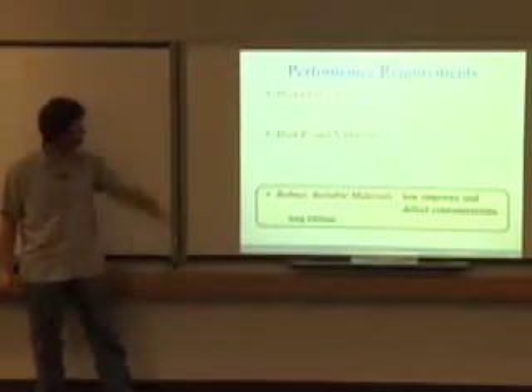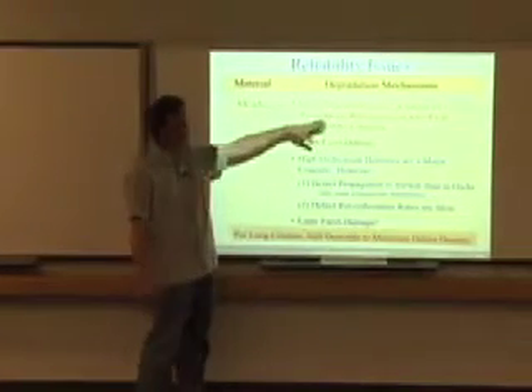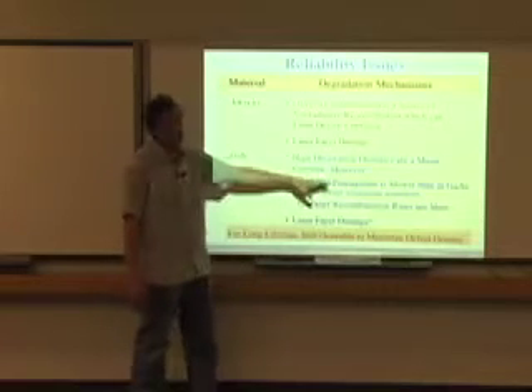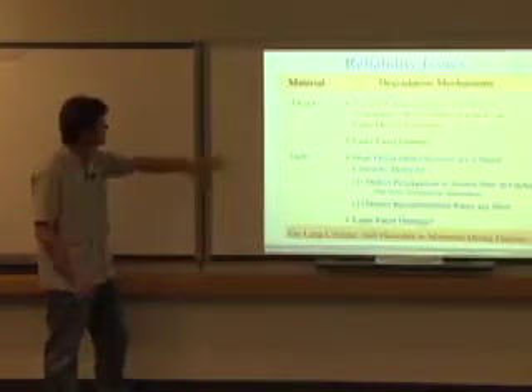So finally, performance requirements, of course, for CW operation and commercial realization, you want robust, reliable materials. In AlGaAs, you have oxygen contamination because of the aluminum, non-radiative recombination, which can occur, laser facet damage, or typical issues. For gallium nitride, of course, we worry about the high dislocation densities. However, defect propagation is slower in gallium nitride. It's a tougher material. Defect recombination rates are slow as well. So even though the defects were very high, it was mitigated by some of these. So actually things weren't quite as bad as you might think.